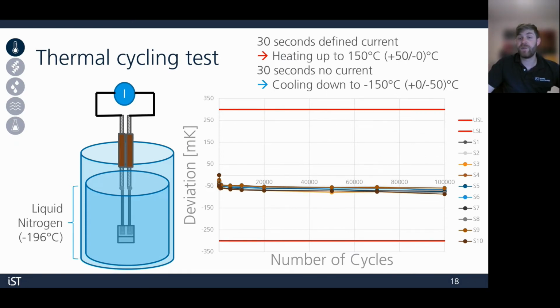Finally, we check how these sensors perform after 70,000 cycles between negative 196, so liquid nitrogen, and plus 200 C. The motivation behind this is an ISS example. So we have a 20-year-long mission circumnavigating the Earth 16 times per day. So we're going to be seeing these cycles between around negative 200 and plus 200. So that's where we get the 70,000 cycle number from.